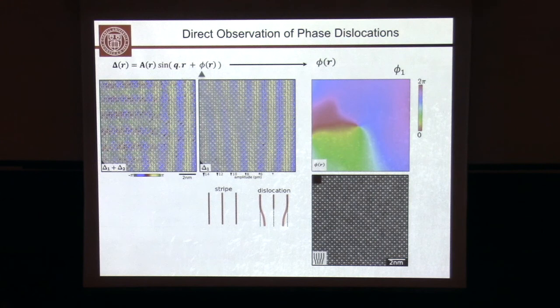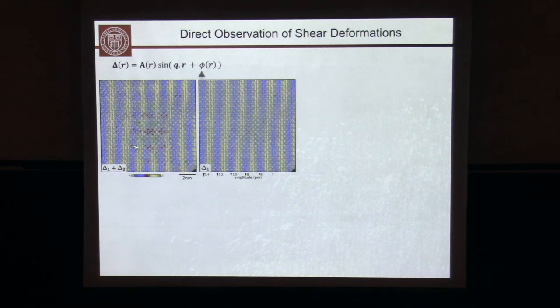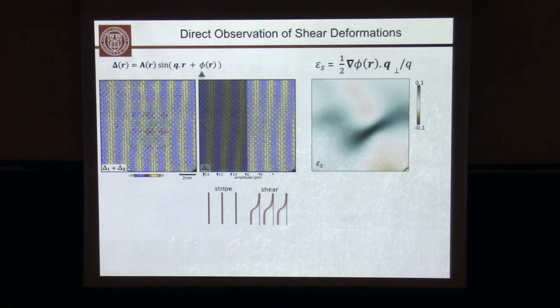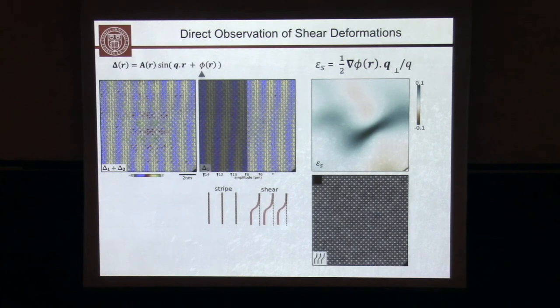So the second area that I pointed out is that where the second phase came up, so the red-green stripes. If we again pull out Q1, if you look carefully, you see that the left stripe is straight and the right one shears. So instead of having ordered stripes, you get shear modulation. We can extract the strain field, and you see strain right in this area. So the picture that arises is that we have local stripe order, but we have defects, phase defects that decorate the material.